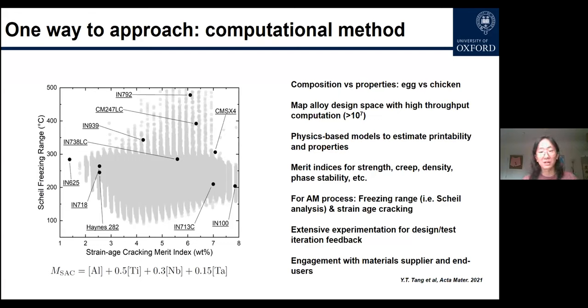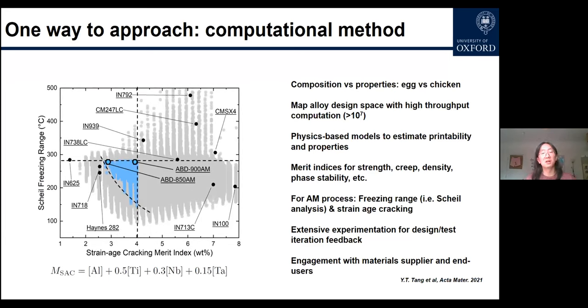So for the additive manufacturing process, we have also incorporated something about processing. One end is the freezing range analysis, essentially the solidification cracking analysis, and the other end is the strain age cracking analysis, which is basically from the welding literature. If you apply some of these criteria, you're basically left with a small area of not so many compositions, and you can do a Pareto front method to analyze what may be the best suitable alloy composition that is within the design scope.